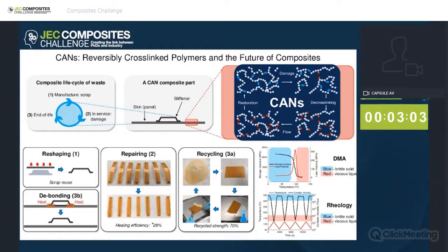We want to repair these cracks, and then maybe we apply a stimulus such as heat or ultraviolet light to the surrounding area, and this may decross-link those blue circles, pull them apart to those red ones, and that gives the polymer backbones the mobility to flow over each other, fill cracks, and repair damage. Now, if we remove the stimulus, our heat or our light, then the crosslinks can reform, and importantly, we can restore the mechanical performance we had to begin with.